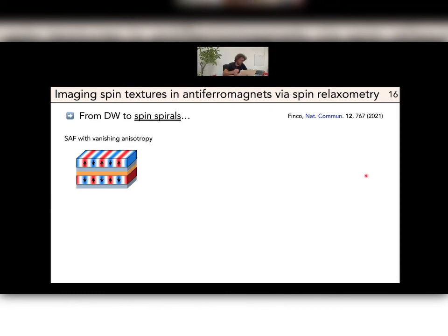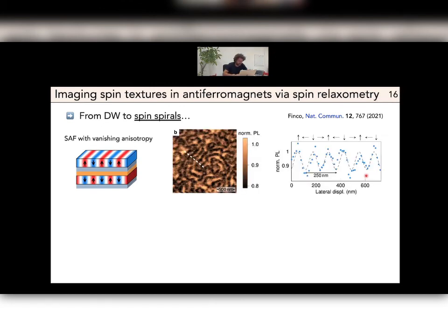Now we decided to do a bit more and look at other spin textures in this synthetic antiferromagnet. The first sample that we looked at is a synthetic antiferromagnet with vanishing anisotropy. Here the cobalt layers were adjusted in order to have a vanishing anisotropy in the sample. In this case, you expect the stabilization of a spin spiral, and this is indeed what we see here. This is a chaotic spiral because there are a lot of pinning sites in the system, but you can see the spiral with a periodicity of about 250 nanometers.